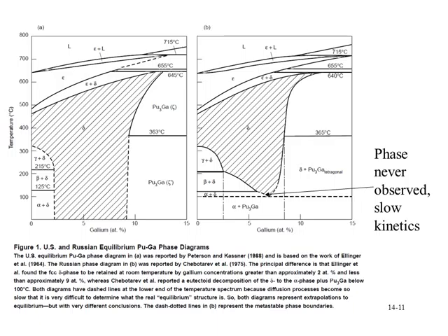Some details of the gallium-plutonium phase diagram are shown here at the low gallium concentration end, and these are the US and Russian phase diagrams. The main difference is that the Russians observed a complicated intermetallic, plutonium alpha phase plus a plutonium-gallium intermetallic, under conditions where the US phase diagram just predicted a single delta phase.